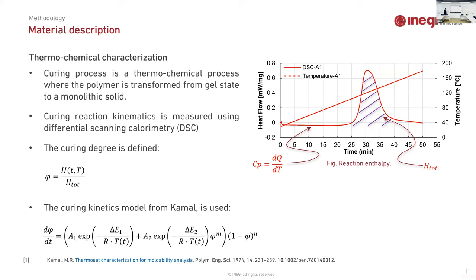How can we characterize that? Since it is a thermochemical process, one of the most used tools to analyze the curing reaction is the differential scanning calorimetry test. We put a sample of the material and measure the heat flow in the material when the curing process happens, and we can extract many things. For example, the specific heat of the resin and the curing enthalpy, let's say the amount of energy that the material needs to release to be cured. This is a quantity that can be measured.